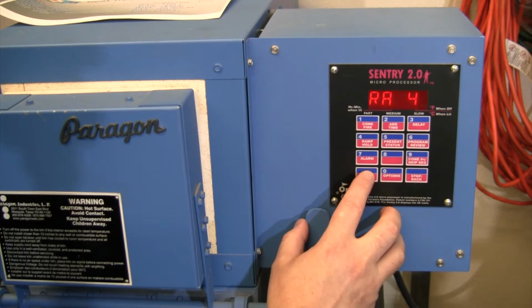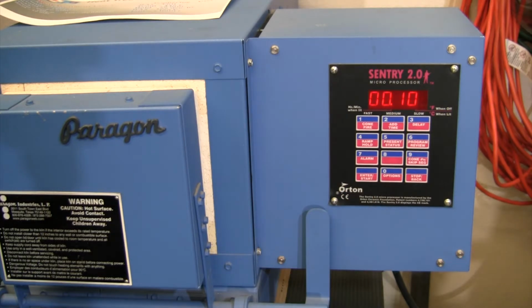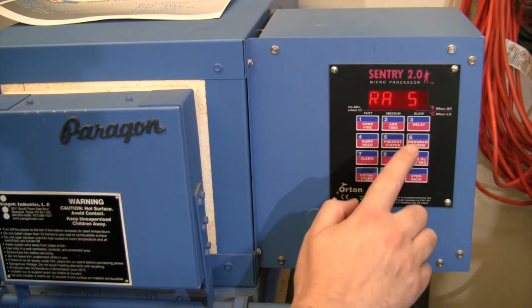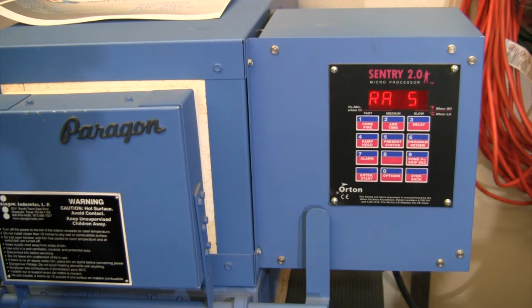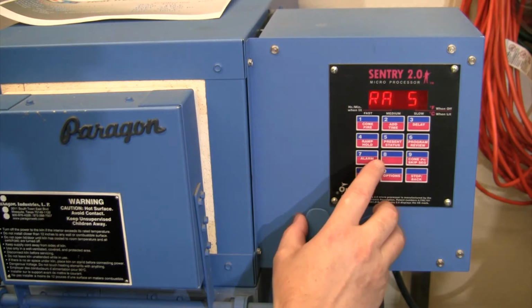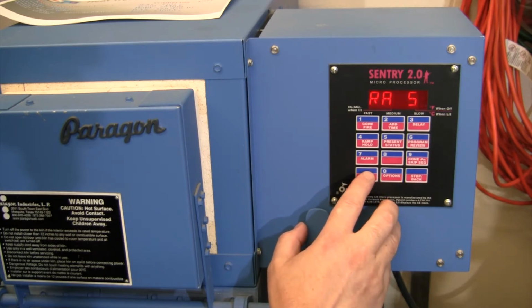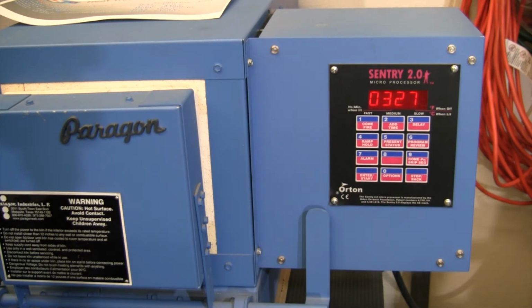Ramp 4, this is now my time to get additional blades out of here, so it's going to hold it full speed, holding it at that 1975, and it's going to do that for an additional 10 minutes. And then that's going to be the end of the program. So this ramp 5 now should be zeros and that tells it that my program can end. Again, you can have up to 10 steps in there on the programs for 2, 3, and 4. So I'm ending at step number 5, and I'm going to hit enter, and we will be back to idle.